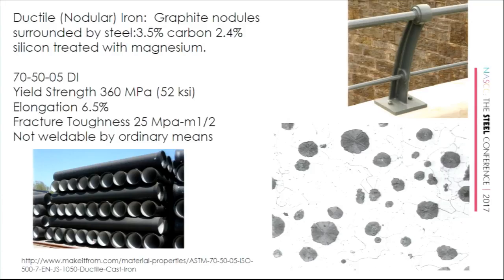They can actually change this by heat treatment to put more carbon in or take carbon out, so they can make it stronger, but they have the trade-off. The stronger they make it, the less ductility they get. They have usable but not fantastic fracture toughness. So any place where toughness is really a concern, or this material is really not weldable by ordinary means because you've got this 3.5% carbon that really limits you.